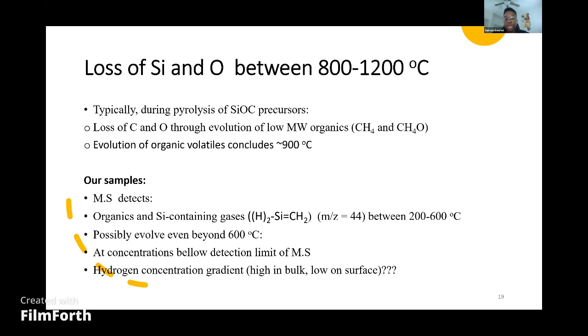Now, our mass spectrometer is able to detect the evolution of organic gases that contain oxygen, as well as organometallics such as silenes, by that I mean silicon double bonded to carbons, such as mass 44, even up to temperatures close to 600 degrees Celsius. Now, although our mass spectrometer can only detect the evolution of these gases up to 600 degrees centigrade, it's likely that these gases keep on evolving even at temperatures beyond 600 degrees centigrade, but at concentrations that are below the detection limit of the mass spectrometer. The evolution of these gases, even at temperatures beyond 800, would then suggest that we would expect to see significant amounts of hydrogen present in the bulk of these materials, although XPS suggests that we don't see significant amounts of hydrogen on the surface of these materials.